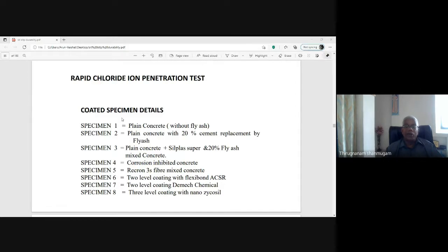The different specimens are with different coatings. Specimen 1 is plain concrete without any supplementary cementitious material, ordinary concrete without any coating. The second is with supplementary cementitious material. Third is with chemical admixture also, superplasticizer. Fourth is with corrosion inhibitor agents, calcium nitrate solutions. Fifth is fiber reinforced concrete. And specimens 6 and 7 are provided with 2-level coating with Flexibond ACSR, Demech Chemical coating on the steel reinforcement as well as on the concrete surface. And 3-level coating with the nano Zycosil means the nano Zycosil is coated on the surface of the concrete, and the surface of the steel is coated with one material, and the concrete is mixed with admixtures, mineral and chemical admixtures. That is the 3-level coating.